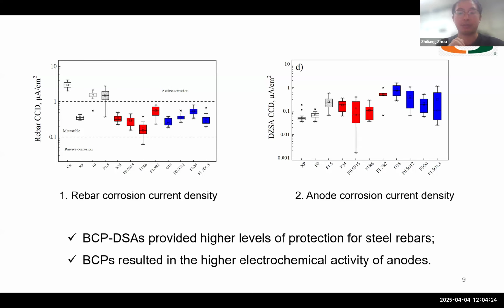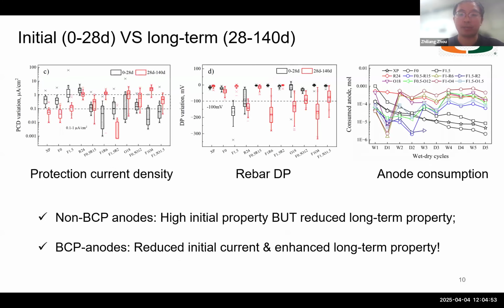And figure 2 gives you the activity of sacrificial anodes. We can see that the color boxes have higher values. It means that the biochar addition can significantly increase the electrochemical activity of sacrificial anodes. And this result can demonstrate the overall activity and the overall protection levels of sacrificial anodes because of the biochar addition. And more importantly, we considered the initial performance and the long-term performance of sacrificial anodes in rebar protection.